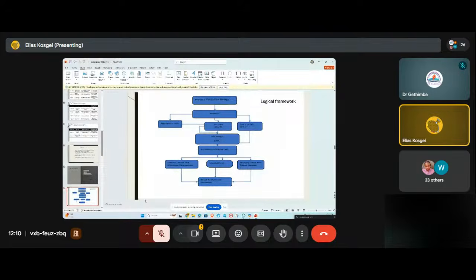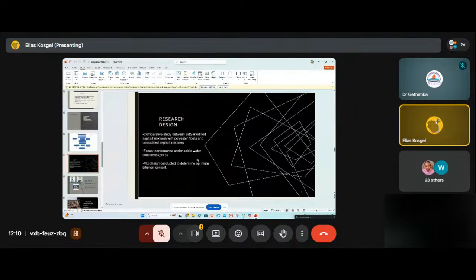From the methodology, this is our logical framework, from theoretical execution to the result analysis discussion. So on the research design, comparative study between SBS modified asphalt mixtures with polyester fibres and unmodified asphalt mixtures. Our focus here will be the performance of this new modified SBS mixture under acidic water conditions of pH 3 and less, and the mix design conducted to determine optimum bitumen content.